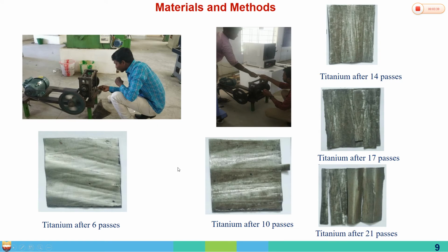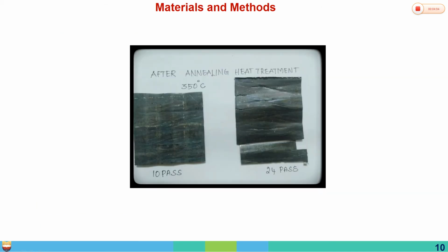These are the students who were involved in doing the experiments. This is the repetitive corrugation technique machine. There are two rollers in the repetitive corrugation and straightening technique. These are the specimens after the number of passes achieved. You can see the difference between the 6 passes and 21 passes, where the material is strengthened. An annealing process was also adopted for increasing the strength.